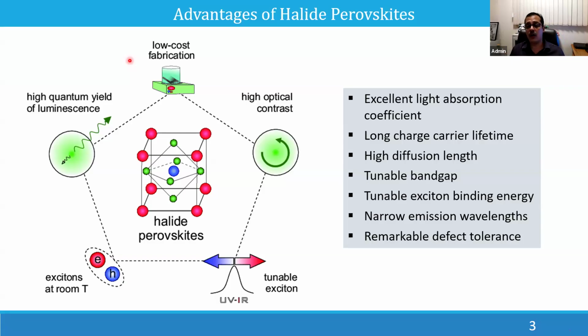And the charge carriers usually have a very long lifetime, so they can easily reach the electrodes without any recombination. And the diffusion length is also very long, like a micron. So these charge carriers can easily travel from the light hitting side to the electrodes, or vice versa, from the electrodes to the functional medium. And as I mentioned, the excitons can be tuned.